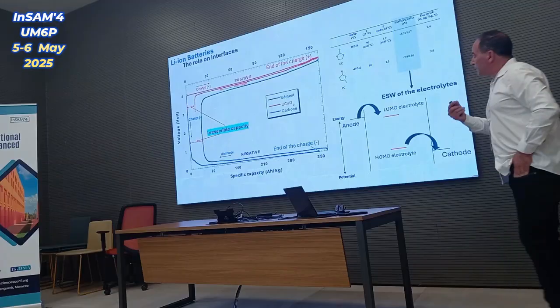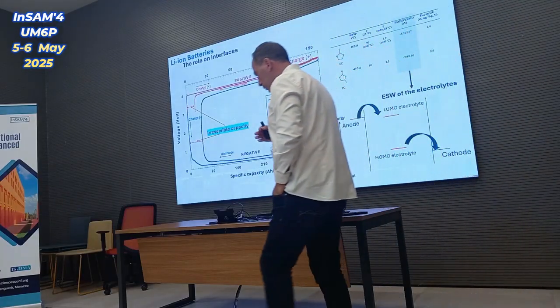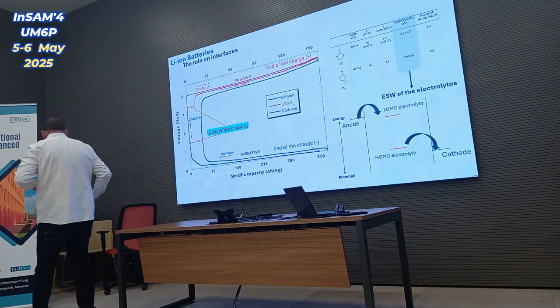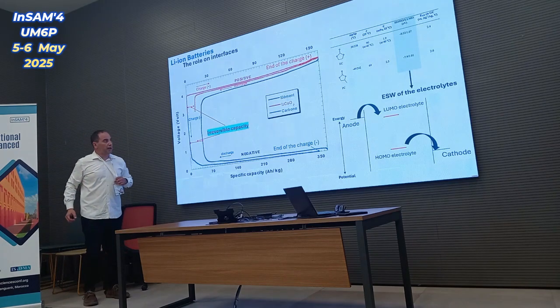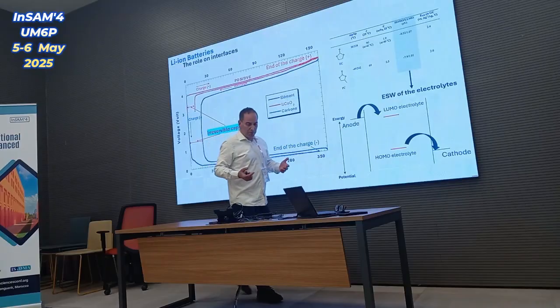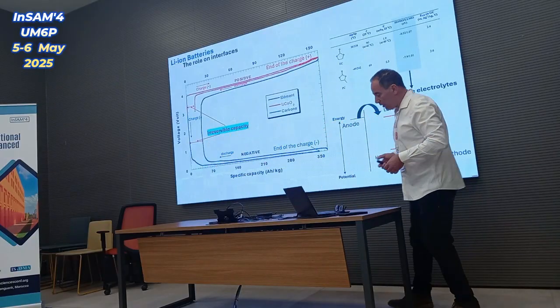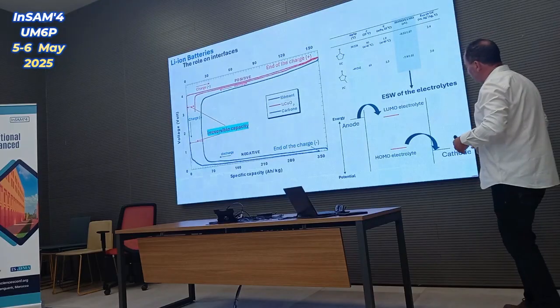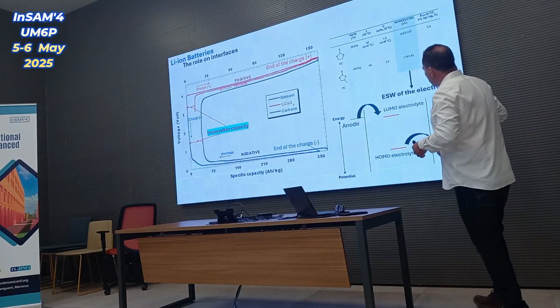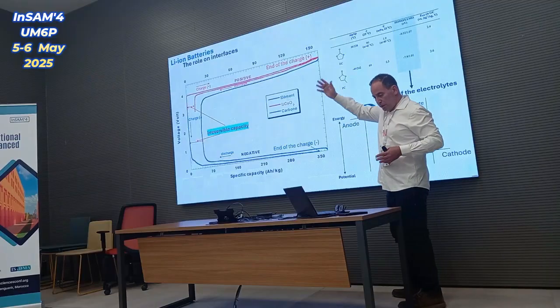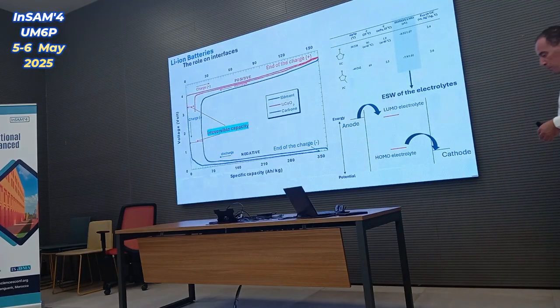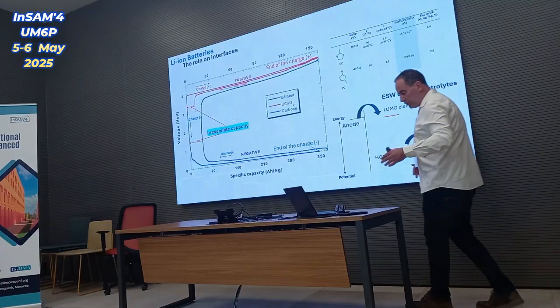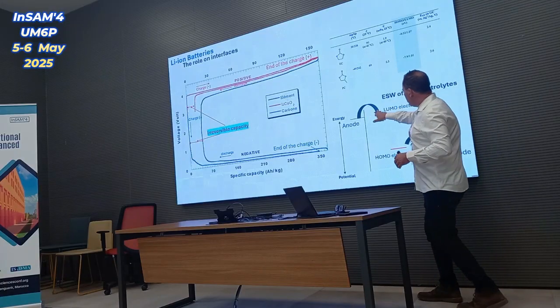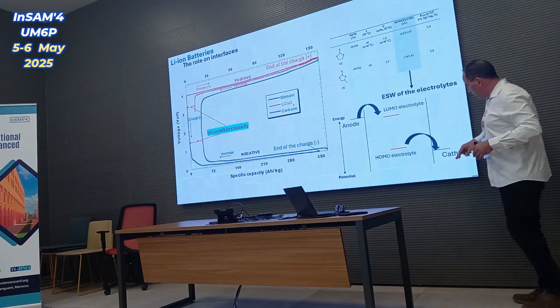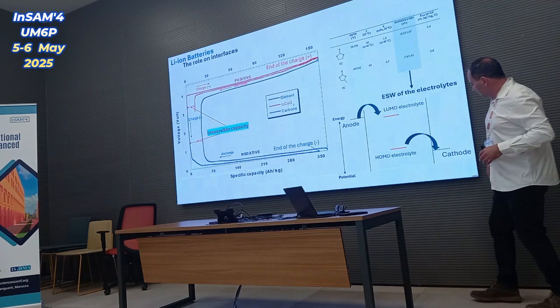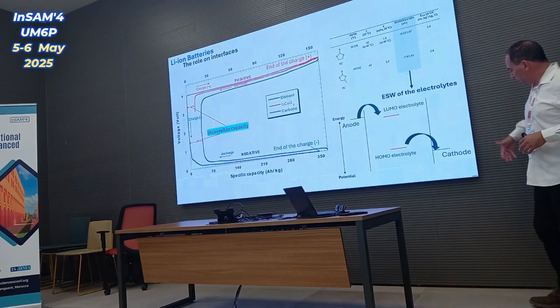So, as I said before, the lithium-ion battery is operating beyond the thermodynamic stability of the electrolyte. So the electrolyte should decompose. And this is actually what happens during charging and discharging, because some solvent component of the electrolyte starts being oxidized at the positive electrode and reduced at the negative electrode. As you can see, it is reduced by getting electrons from the anode, the negative electrode, and here it is oxidized, providing electrons to the cathode.